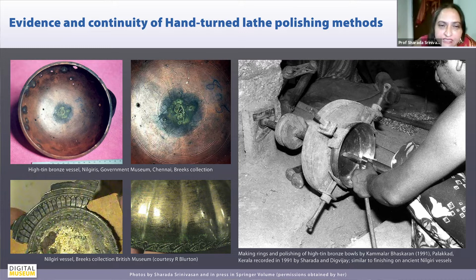And they also have these very delicate patterns, these lotus patterns and so on, incised patterns. And again, it had been thought that because they were so sophisticated, they may have come from somewhere else. But as I was also pointing out, some of these workshops still follow many of these practices. In fact, when I was there in Palakkad in Kerala in '91, they were still using these hand lathes, where they mount the vessel onto a lathe and then use these steel chisels and points to make the patterns. And you can also see the evidence of this lathe turning, for example, on this vessel at the bottom from the Nilgiris, where you see the lines from the lathe turning, apart from all these lotus motifs and such like.